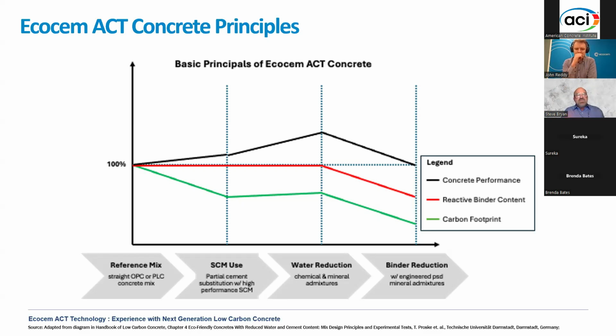And if you simply move to use of a high performance SCM like slag, you're able to maintain the same amount of cementitious. You get a major reduction in the embodied carbon, and you actually get a little bit of increase in performance, particularly in long-term strength. The next step is if you take out water, reduce the water cement ratio using water reducers, superplasticizers, you're able to significantly increase the strength from there.